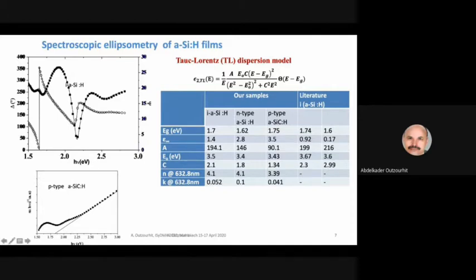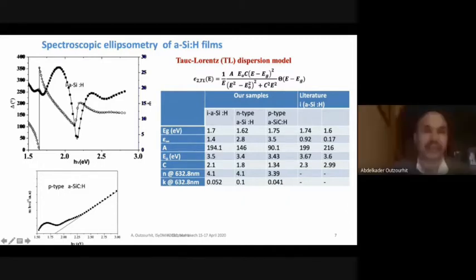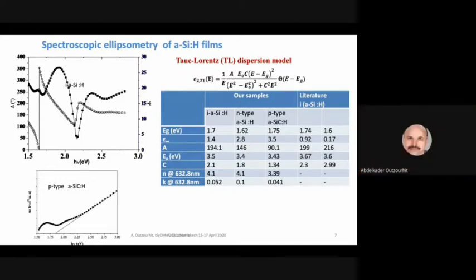We also performed some optical measurements, transmittance measurements, in order to obtain the absorption coefficient of the films. And this is a typical representation using Tauc's law of the absorption coefficient, which shows the existence of a straight line portion, and the extrapolation of this straight line enabled us to determine the optical band gap of the film. In this case, for this particular film, the optical band gap is around 1.78 electron volts, which is rather close to the values obtained from the spectroscopic ellipsometry measurements. So these are complementary techniques that were used to determine some of the optical parameters of our layers.